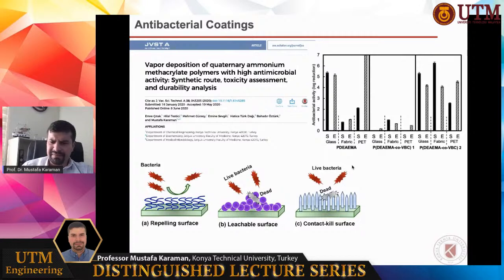Silver has a leaching mechanism to kill the surface, but I think in the near future the use of silver will be banned, because silver not only kills the harmful bacteria but also kills the harmless bacteria, and the leaching mechanism also develops antibacterial resistance. So our advantage is that our thin films are kept on the surface, the mechanism is contact killing, and the materials do not leach into the atmosphere or into the water.